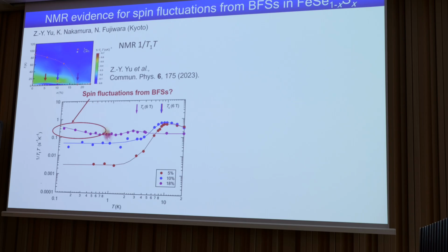For this purple data, which is in the SC2 region, here is TC. Usually 1/T1T gets smaller if you go to low temperature in the superconducting state. However, it's a very surprising result that in this SC2 region we have an increase in 1/T1T at low temperatures, which is quite anomalous behavior.